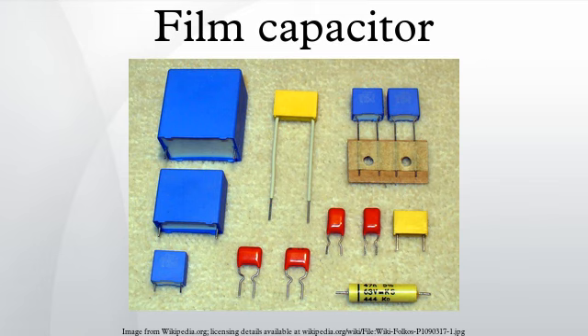Thermal stress during the soldering process can change the capacitance value of leaded film capacitors by 1% to 5% from the initial value, for example. For surface mount devices, the soldering process may change the capacitance value by as much as 10%.